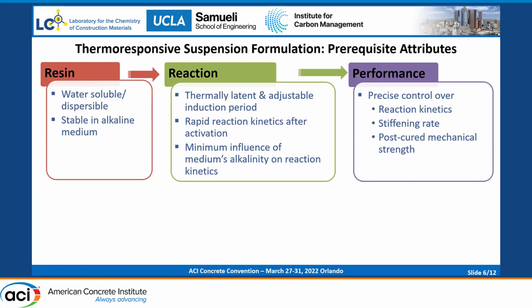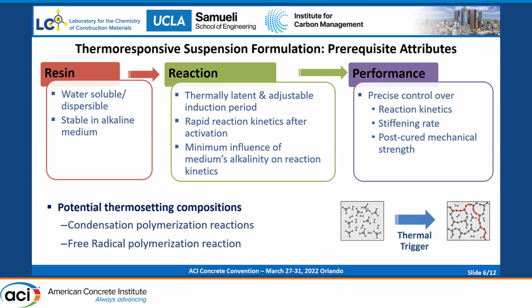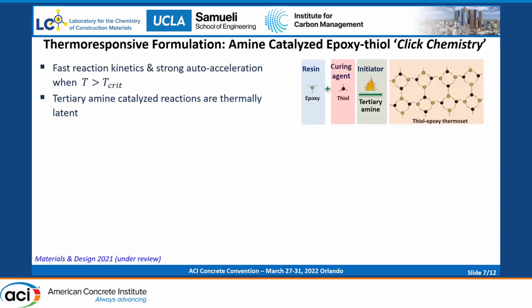And in terms of performance, we should have precise control over the reaction kinetics, the stiffening rate, and the post-cured mechanical strength. So we primarily focused on two reactions: condensation polymerization reaction and free radical reactions, basically using a thermal trigger to induce the gelation within the matrix. So I'm going into the details of one of the thermoresponsive formulations that we developed, that is based on amine-catalyzed epoxy-thiol click reactions. The reason we chose this reaction is because it has very fast reaction kinetics.